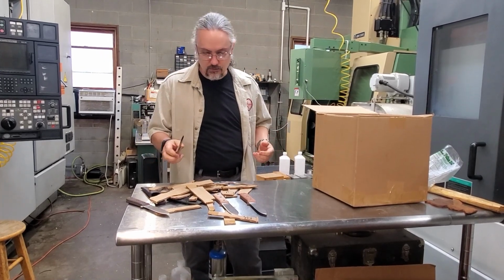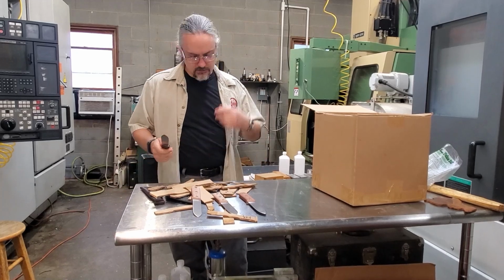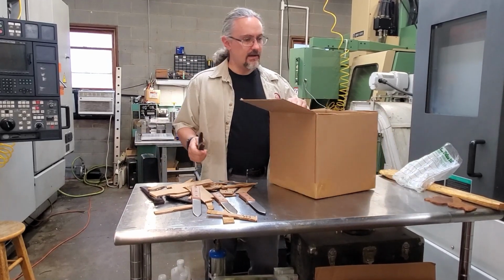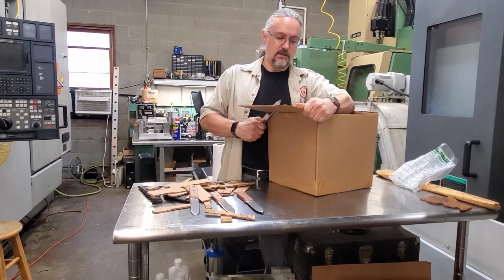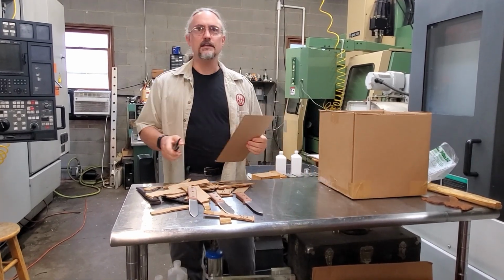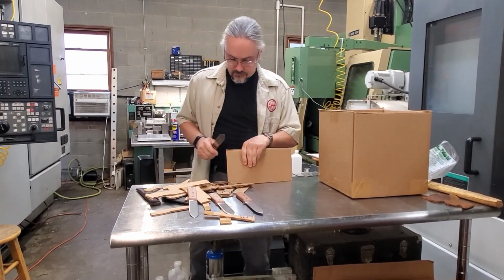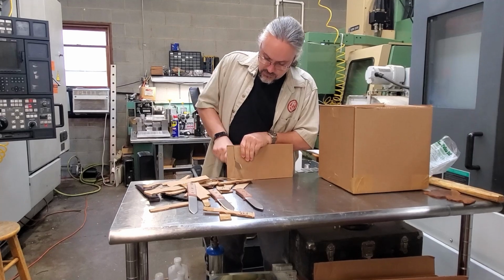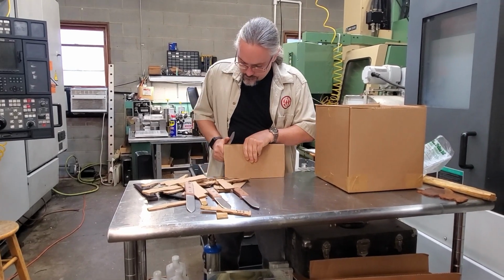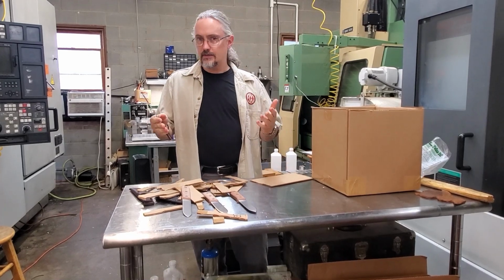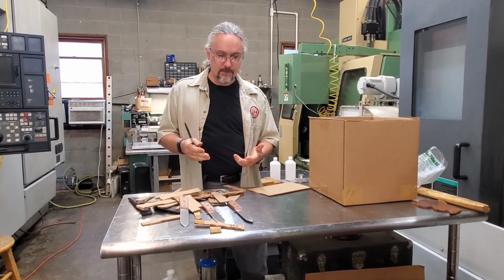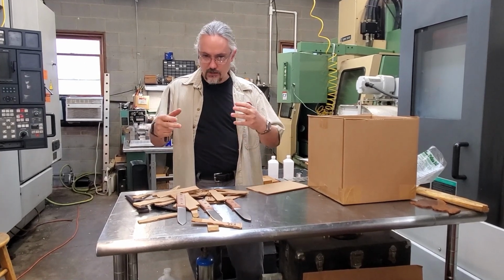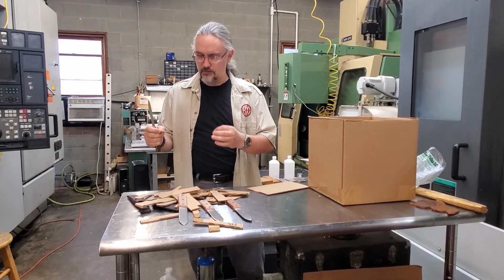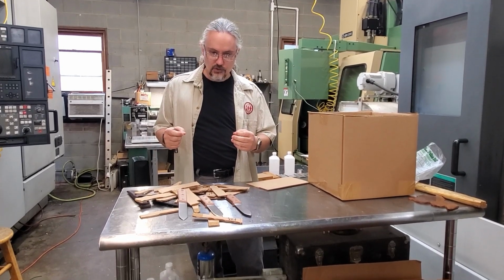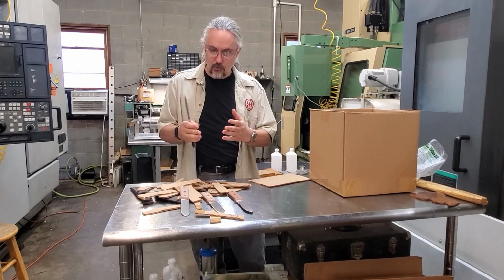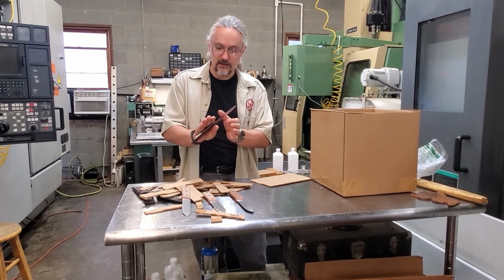And so in a tool and die steel like 3V, or like a D2, which is where we first started messing around with these low temp tweaks, you will have an opportunity to utilize a heat treat that does not use that secondary hardening hump. The reason you might want to do that is because you're able to keep the carbon tied up in the martensite, which is where you want it. If you've got really hard, strong martensite and slightly smaller carbides, you're going to have a structure that is able to hold an edge better at the narrow angles of a knife edge.